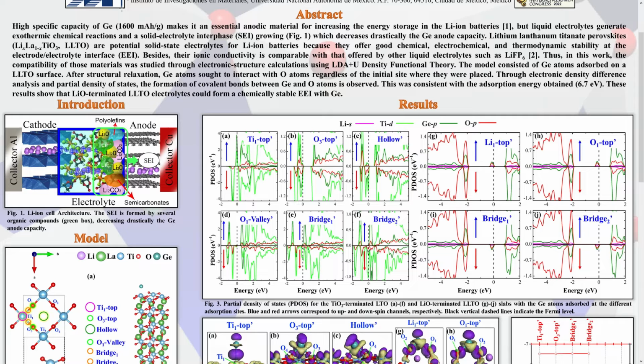Thus, in this work, the compatibility of those materials was studied through electronic structure calculation using LDA plus U density functional theory. The model consists of germanium atoms absorbed on a lithium lanthanum titanium oxide surface. After structural relaxation, germanium atoms sought to interact with oxygen atoms regardless of the initial site where they were placed.